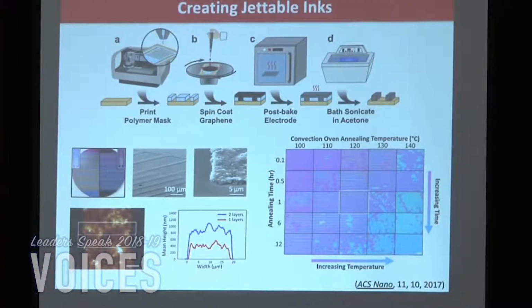So this is a silicon wafer in the back. But we've made all these, what's called an interdigitated electrode. It just has two finger-like combs that are coming together and creating a type of circuit that works well for biosensors. And we're able to get down to a line resolution to make those little finger combs about 20 microns. And that's really good because photolithography can get a little bit lower than that, a few microns in line width, but not too much lower than that. And we didn't have to do any clean room processing, so it's a pretty inexpensive technique to do. And we can control the layer thickness by spinning on more graphene and so forth. So it's just a fabrication technique to make these type of electronics.